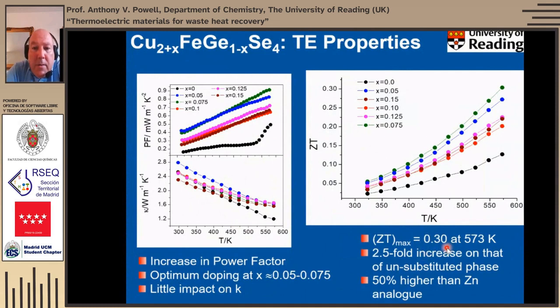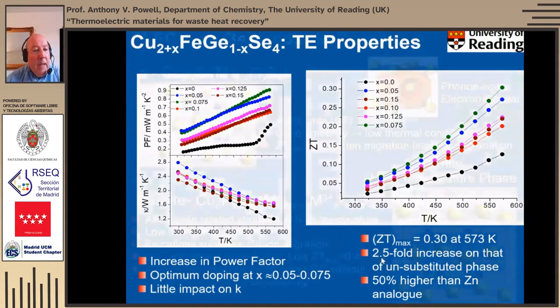So the net result is that we now get up to a figure of merit that's about 2.5 times that of the unsubstituted phase, and significantly, in view of the fact we were trying to get an improvement as a result of a magnetic ion being here, about 50% higher than that of the zinc analog. So we're up at about 0.3, but I would stress at quite low temperatures, at about 300 degrees centigrade. So it's quite useful for industrial waste heat type applications.